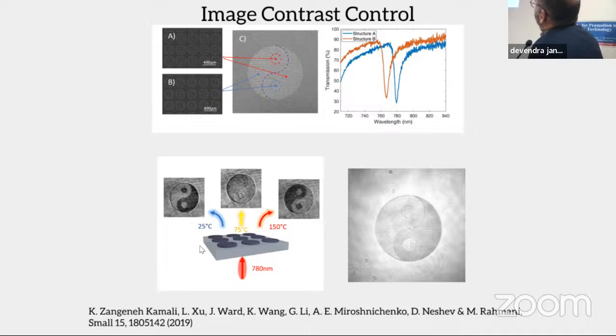So this yin-yang structure is fabricated based on these two building blocks, which are resonant at very close by wavelengths. As a result, when you heat the sample from room temperature to only 150 degrees, which is much less than 300 in the previous slide, you can completely go from one phase to another. As you see, it is the exact same structure, and this is the image of the structure in the electron microscopy. And here is the optical image of the exact same structure, and you can see this black and white. And when you heat it, you go from one phase to another.